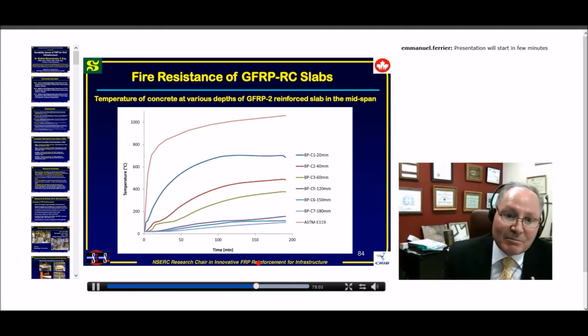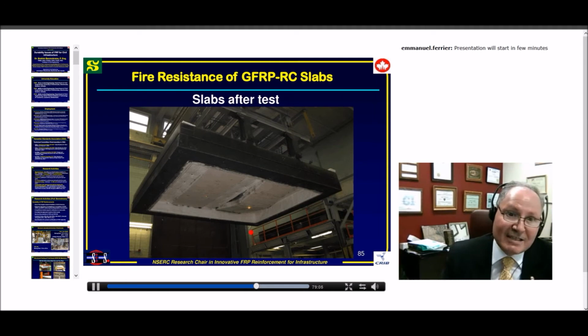And the most important result is that both slabs did not fail after 3 hours, which is really 1 hour above the minimum required, which is 2 hours. One slab, you can see it here, lasted about 3 hours and 10 minutes. And we were really so happy, and